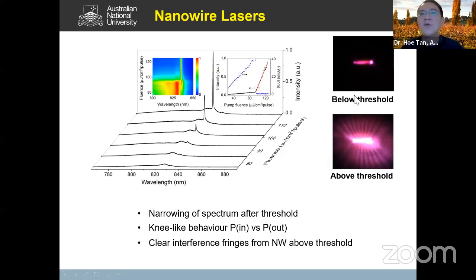And yet another proof that our nanowire is lasing is from the optical image here. If you look from the top, the nanowire has just a glow before threshold, and after threshold, it forms these interference fringes. Interference fringes essentially occur from the interference between the light coming out from the two end facets of the nanowire. And again, interference can only occur when the emissions are coherent, okay? Which means the nanowire is lasing.